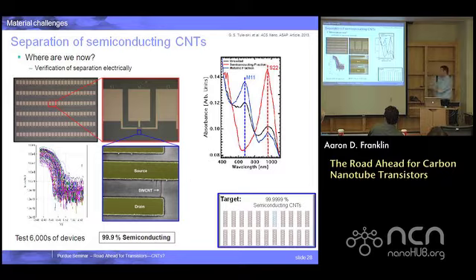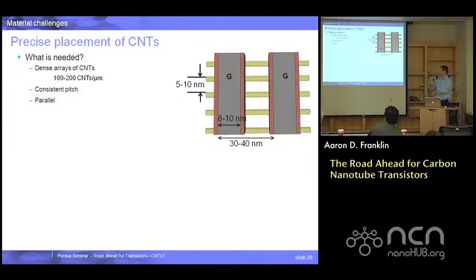And in this case, the best we have that I'm showing on this slide is 99.9%. And that's good, that we can give some real data towards that, but we're never going to build enough devices and have enough hours to test something that gets down to the 5 or 6 nines range. So this is a real big materials issue that we've actually started a new collaboration with the folks at NIST, because this is what they do. This is material measurement and characterization, to try to figure something else out that can give high throughput, better accuracy on knowing what type of purity is present with nanotube solutions. Okay, so that's one of the materials issues.